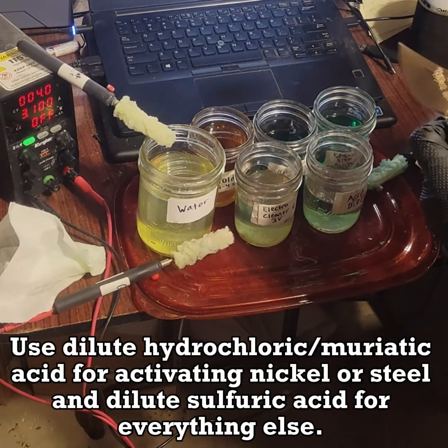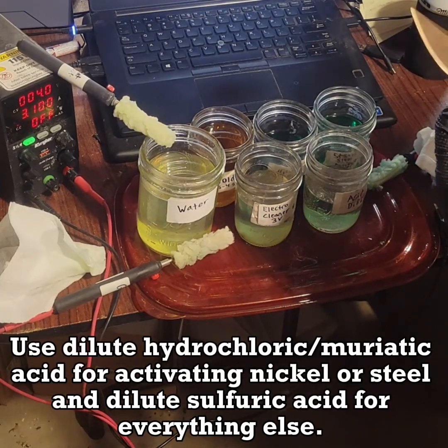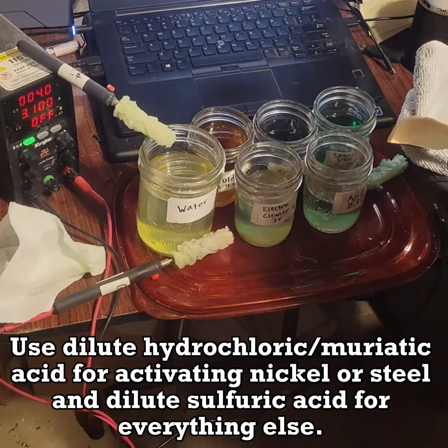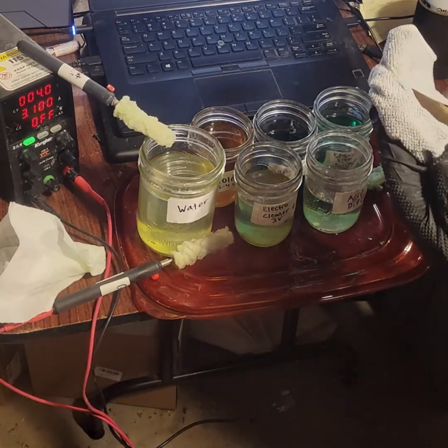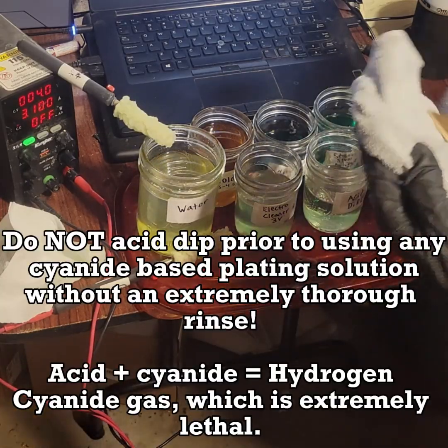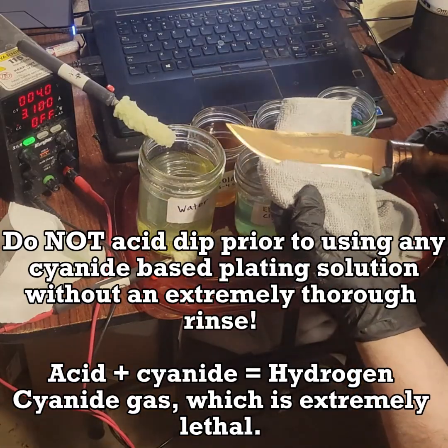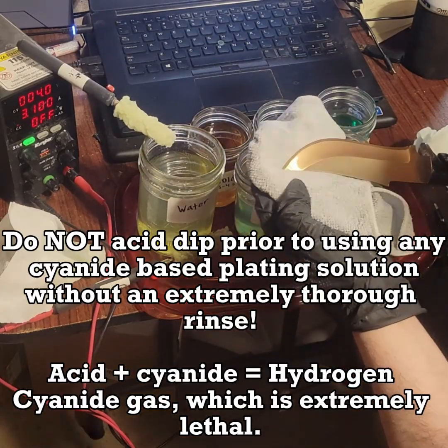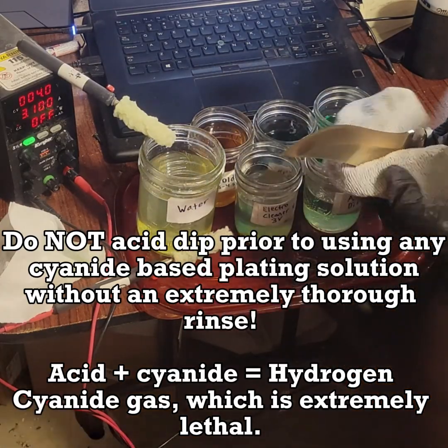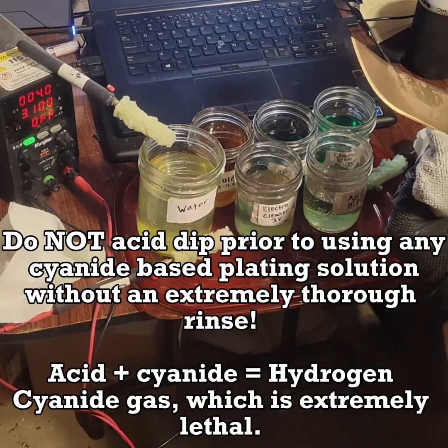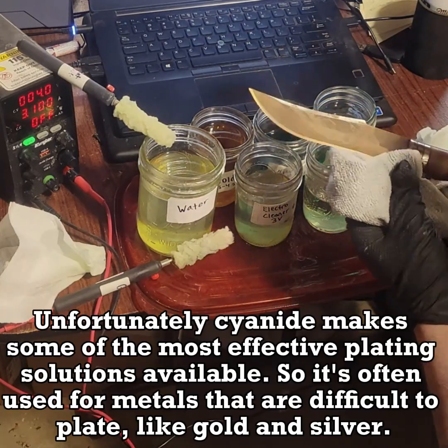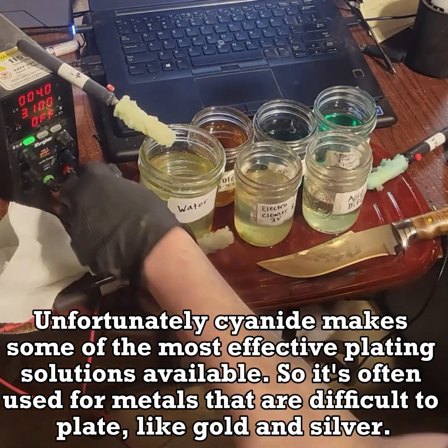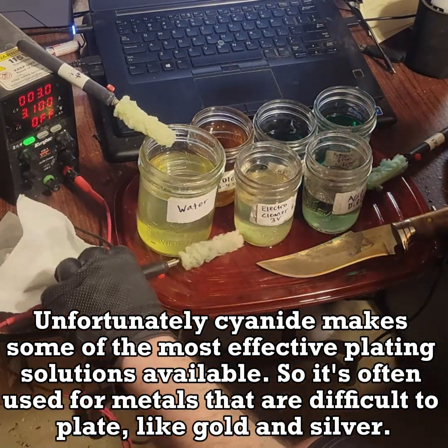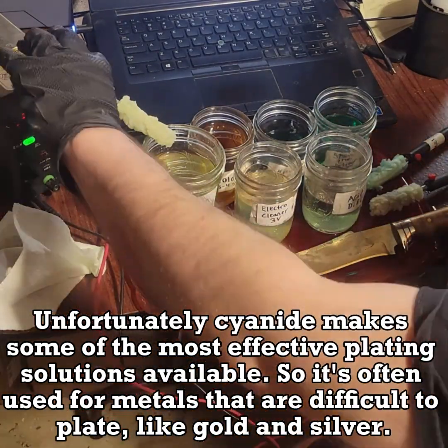Use dilute hydrochloric muriatic acid for activating nickel or steel, and dilute sulfuric acid for everything else. Do not acid dip prior to using any cyanide-based plating solution without an extremely thorough rinse. Acid plus cyanide makes hydrogen cyanide gas, which is extremely lethal. Unfortunately, cyanide makes some of the most effective plating solutions available, so it's often used for metals that are difficult to plate, like gold and silver.